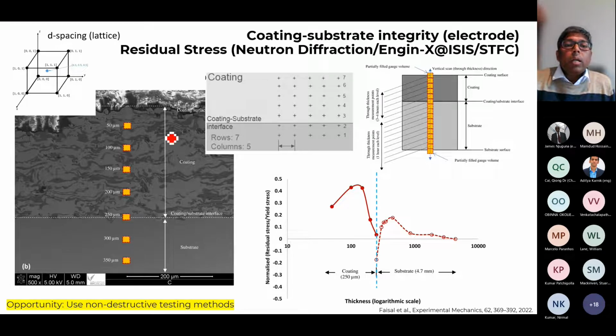This is an example where the same material we put in front of a neutron beam. And what we did, we selected a few points in the coating. One point at the interface, or as close to the interface, and a few points in the substrate. So this is the electrode substrate. This is a coating about 300 micron thickness, just over 250, I believe.